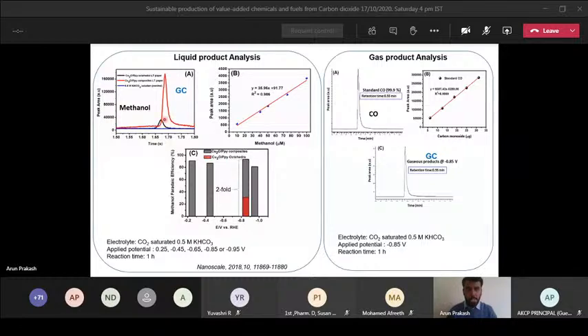You can observe blank, there is no signal for methanol, but after CO2 reduction, you can observe a peak for the octahedra shaped particles on the paper electrode. But this one is almost 2 or 3-fold higher for the composite paper. And we quantified our product using GC, and we confirmed we got a single product, methanol, in our liquid system, and the activity of the composite electrode is almost 2-fold higher than only octahedra. So that's why I told, depending on the shape of the particle or the size, you can tune the activity.